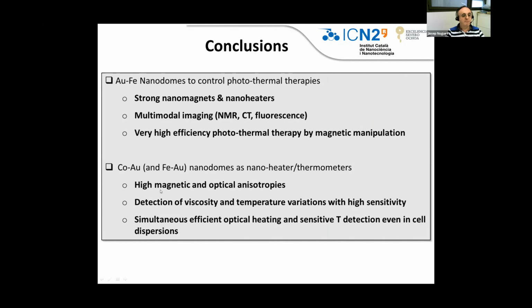Because they have high magnetic and optical anisotropies, which we use for rotation of the nanoparticles and for the sensing. We can detect the viscosity and temperature variations with high sensitivity. And we can simultaneously and efficiently optically heat and sensitively detect the temperature even in cell dispersions.